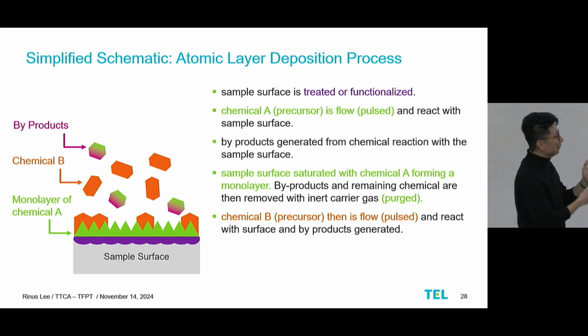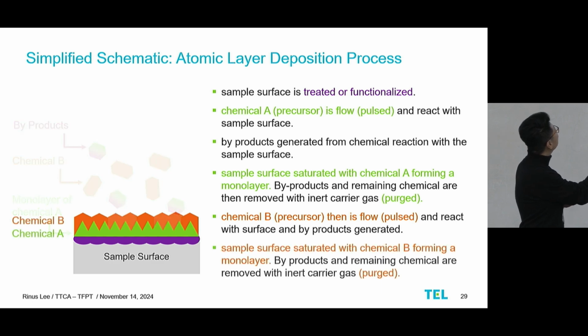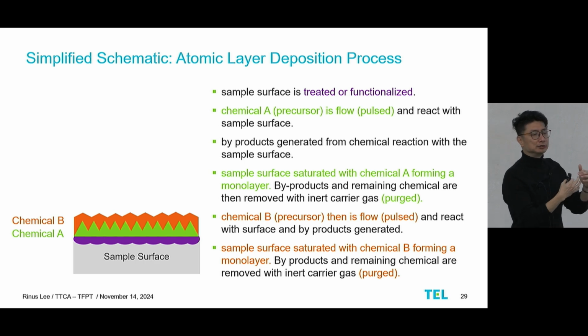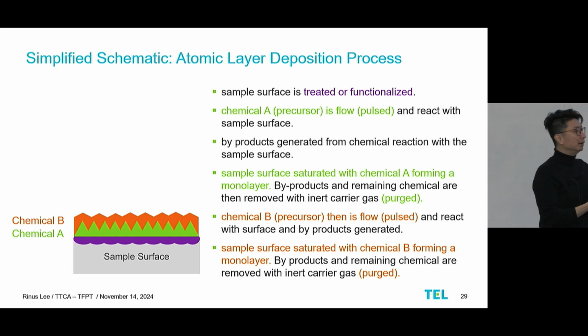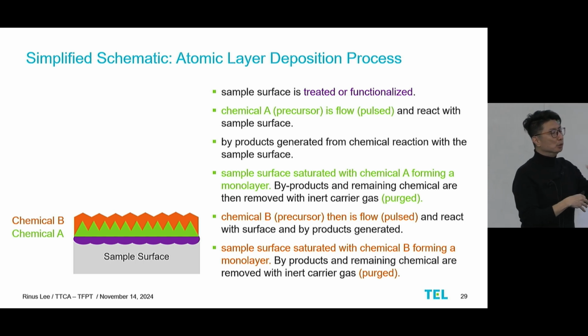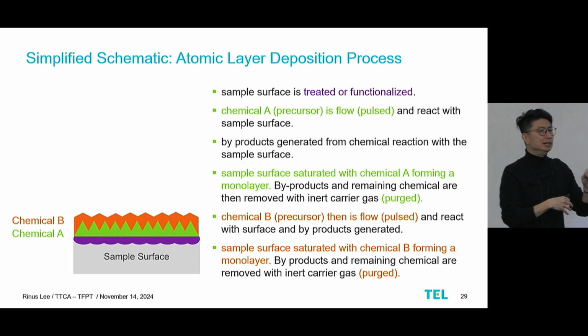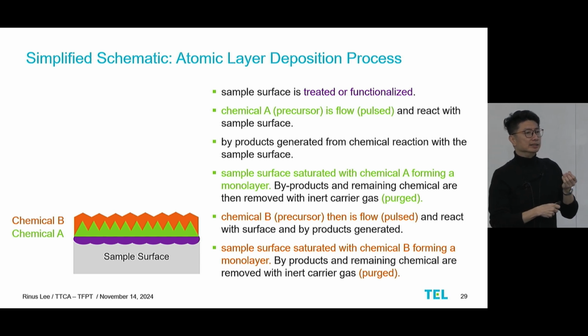By doing this chemical A and chemical B rotation, you could see once again chemical B, orange shapes, coming down onto the surface and reacting with the chemical A. There will be byproducts generated. And then similarly, when enough chemical B comes down to the surface, it will just self-saturate because there are no more sites for chemical B to react with chemical A. And then similarly, we will introduce the inert gas and bring out all the remaining chemicals. So you could see here what happens is, by reacting two chemicals together, we have a monolayer of a dielectric film or a metal film, typically about 1 or 2 nanometers in thickness itself.